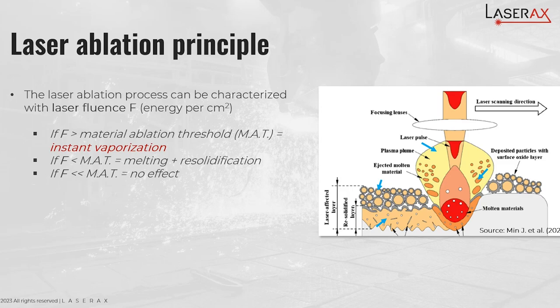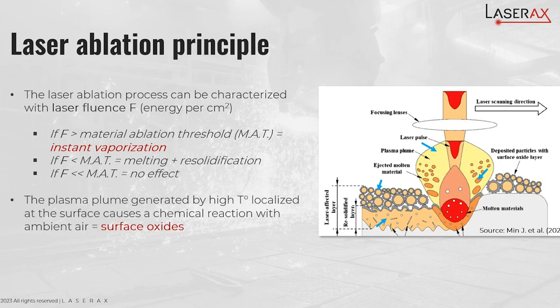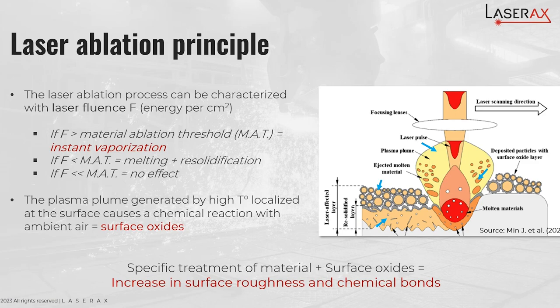This phenomenon causes a change in the roughness and the pattern on the surface. Additionally, you have a plasma plume that is generated at the interface of the laser and the material. That plasma plume creates an environment in which chemical reactions with ambient air are favorable, and that causes a layer of surface oxides on the surface — not to be confused with typical oxides that we don't want on our surface. The addition of that treatment, that change in roughness, and these surface oxides increase the overall surface area to bond, as well as the chemical bonds on the surface, which in theory increases adhesion. And that's what we wanted to demonstrate with this project.